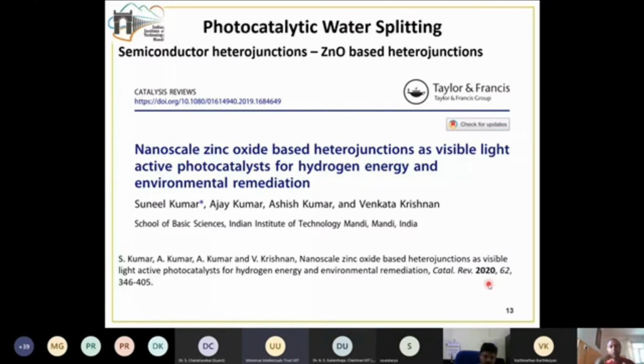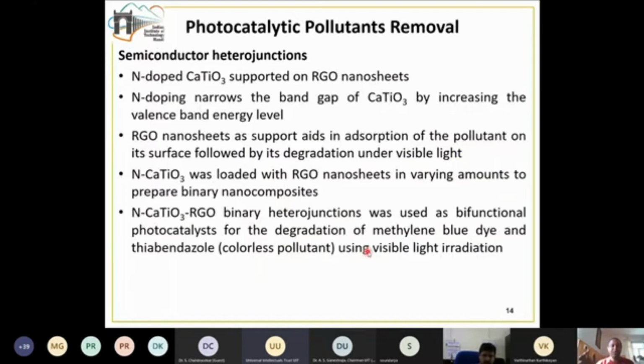Now we are moving on to another type of material. We have been talking about zinc oxide so far, but can we get an even better material or other material here? So we focused on other types of semiconductors as well, wherein we focused on calcium titanate. In this calcium titanate, we also took nitrogen doping to change the band gap by moving the valence band position, and then supported this nitrogen doped calcium titanate on reduced graphene oxide sheets, the RGO sheets. And here the nitrogen doping again narrows down the band gap by increasing the valence band level.